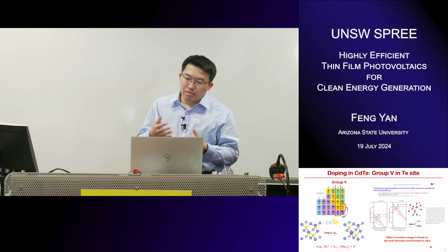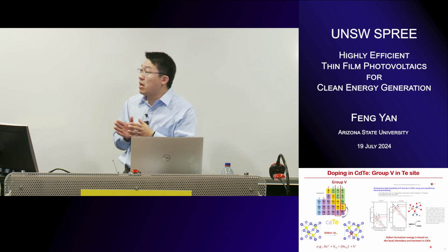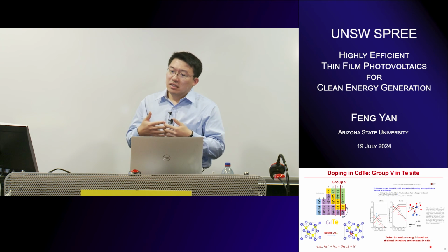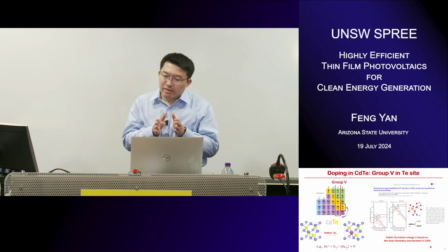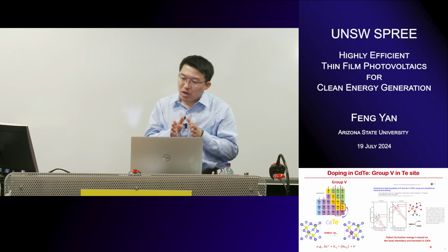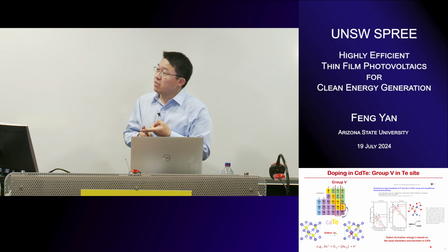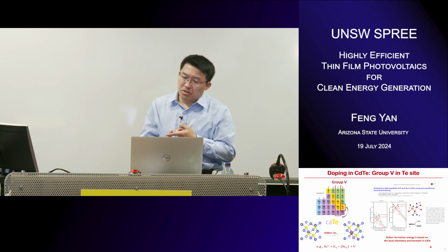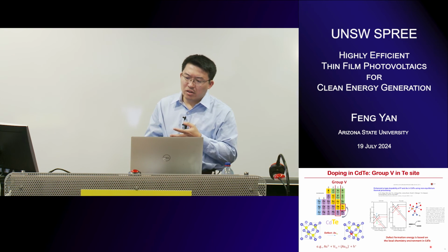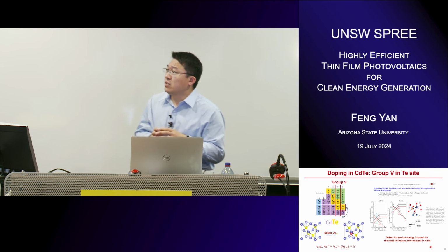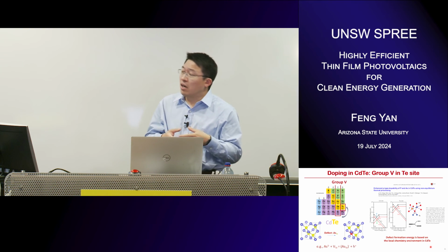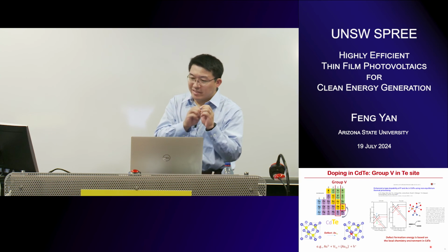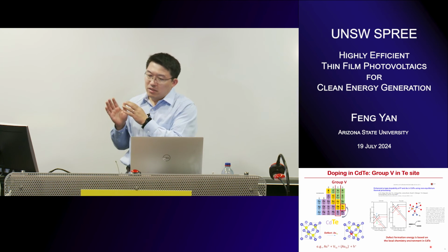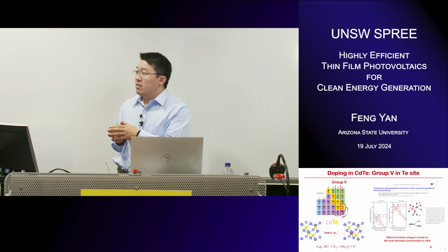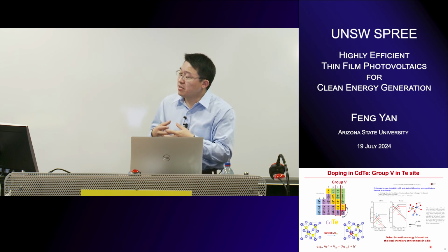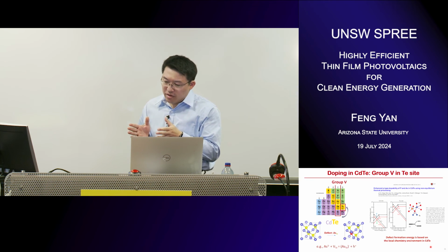If we talk about the passivation, the grain boundary has a lot of dangling bonds, right? So that's the defect. From the material science side, the major role of the cadmium chloride is grain growth and reducing structural defects, including stacking faults, dislocations, and also a lot of physical voids. The material science people observe the grain size growth, grain boundary, and stacking faults using TEM or whatever. The physics people talk about passivation and recombination, how the carriers transport in the grain boundary. That's true, the passivation role is significant.